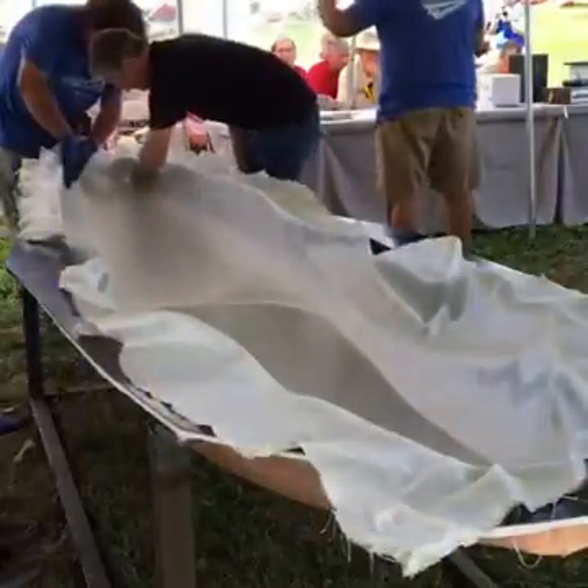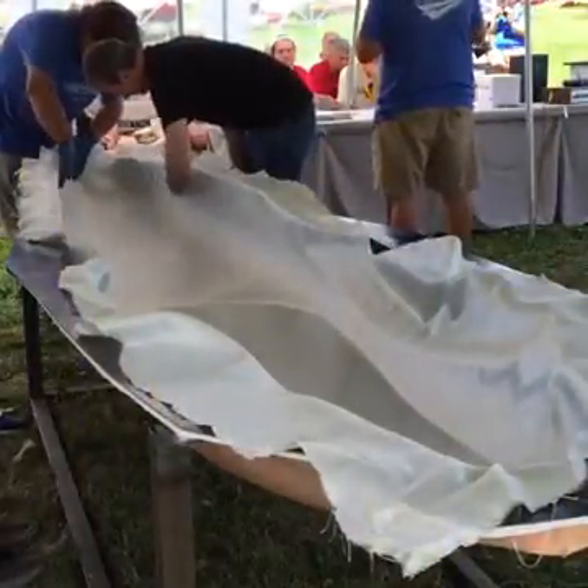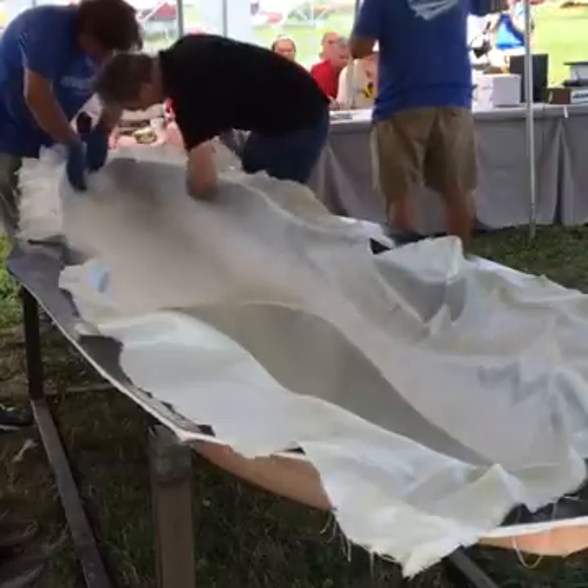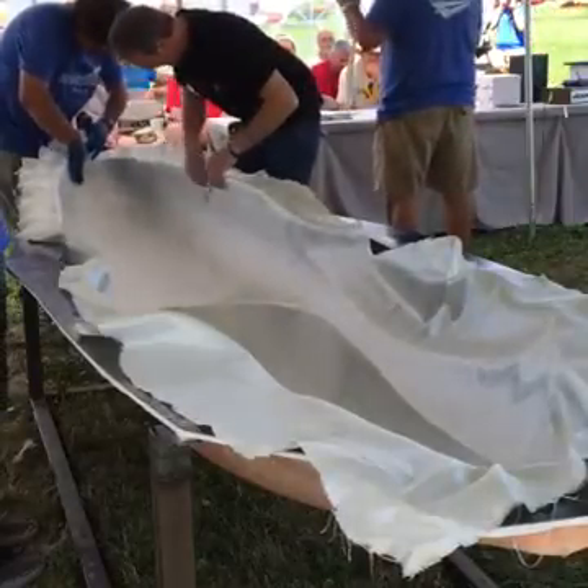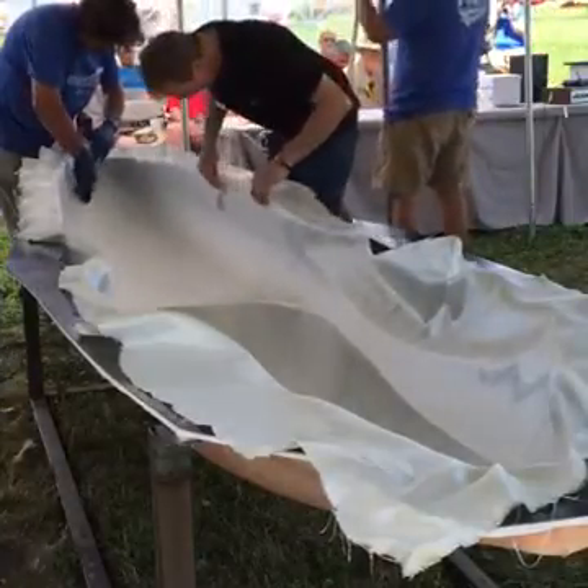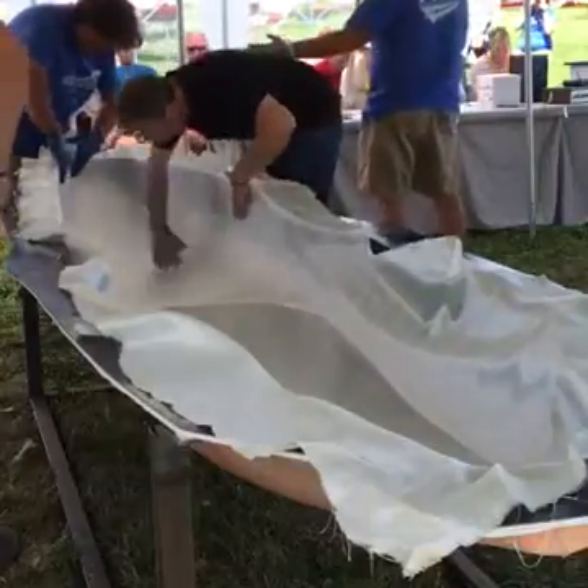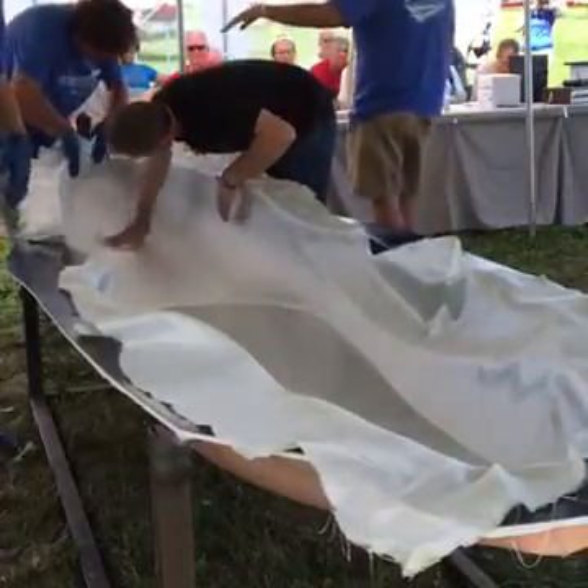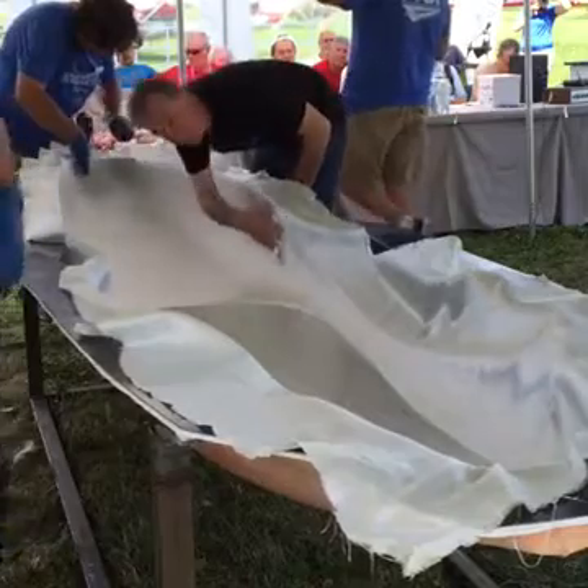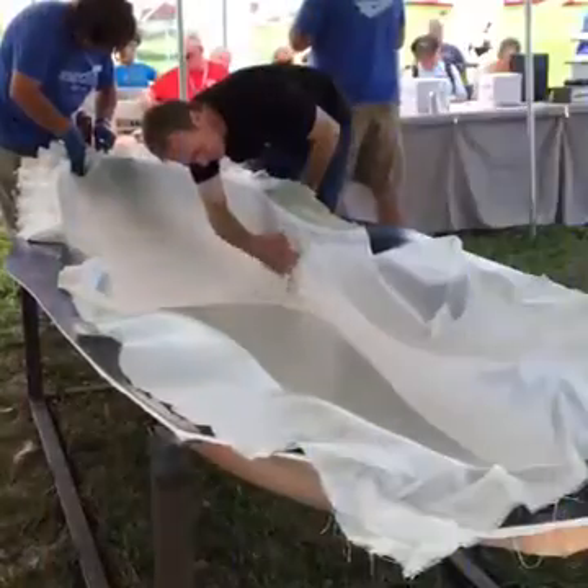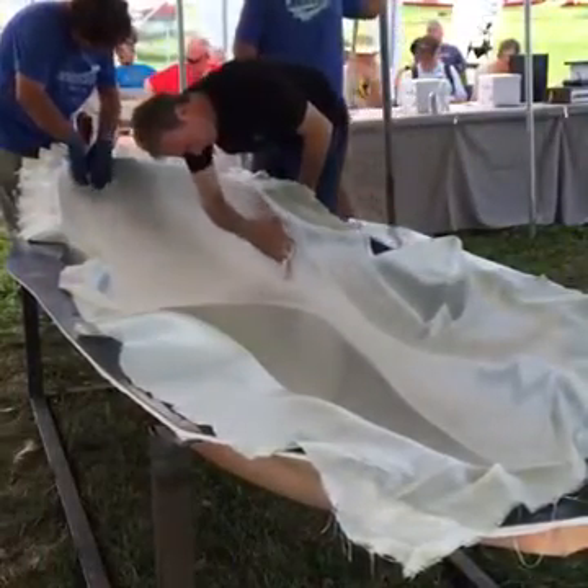So any post-cure that you do after that really shouldn't have a lot of effect, but we find it gives a nice glossy surface. And in case you do take the part out immediately and set it out in the sun, you can put it back inside, real quick into the die, or into the mold, and let it sit there overnight, just in case there is any shrinkage that goes on. That's it. I have a couple questions.